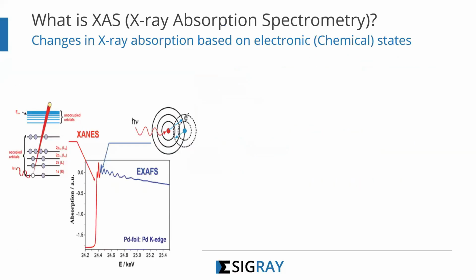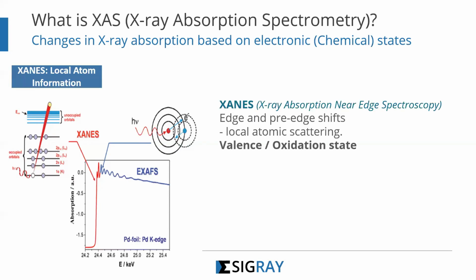Now, let's take a look at what XANES is and what EXAFS is. Every element has its own characteristic, what you call the chemical edge. It is the energy at which, when you impinge a material with a specific energy, a certain absorption takes place that is very sharp. That is called X-ray absorption. This is called X-ray absorption near-edge spectroscopy, where you study the edge and the pre-edge shift. I'm going to show you what the edge and the pre-edge are in a little moment.